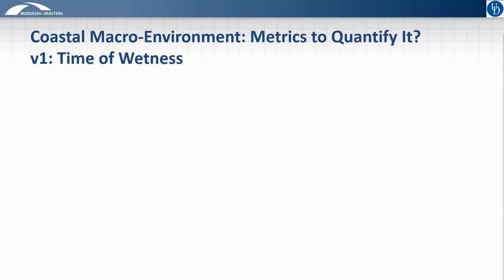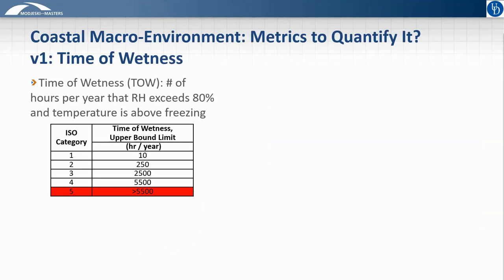To get more specific, we have two possible definitions of humidity. The first is based on time of wetness, where time of wetness is the number of hours per year that the relative humidity exceeds 80% and the temperature is above freezing. With 60% time of wetness, equaling 5,500 hours per year, being generally accepted as a threshold for concern. And this is labeled as Category 5 by the International Standards Organization, or ISO.